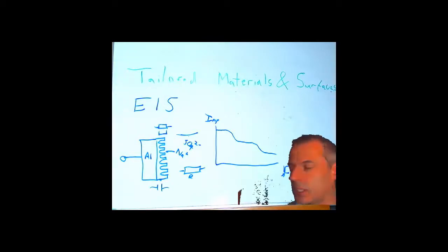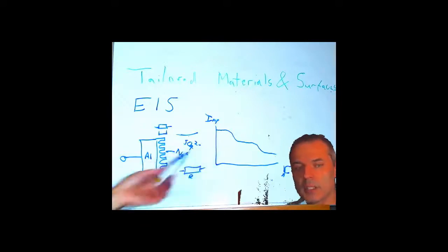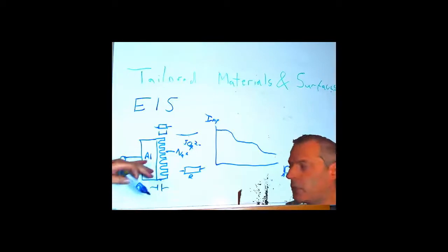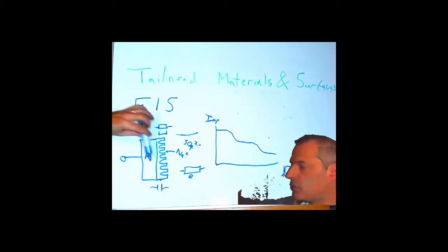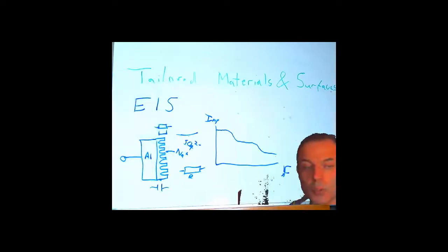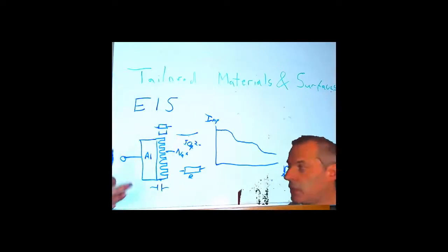The difficulty, as I said at the beginning, or I might have forgotten because I had to record this twice, the difficulty with this technique is usually in analyzing the data without making too many assumptions. It's relatively easy to do it with aluminium and aluminium oxide because we can form a thin layer of aluminium oxide and we can grow it thicker and thicker. So we've got comparison specimens. But if we've got something unusual, then it's difficult to see anything.